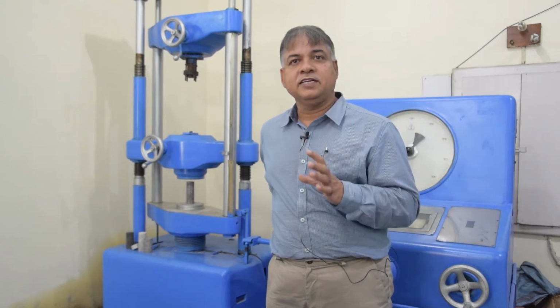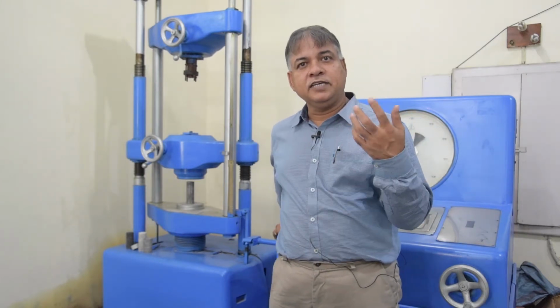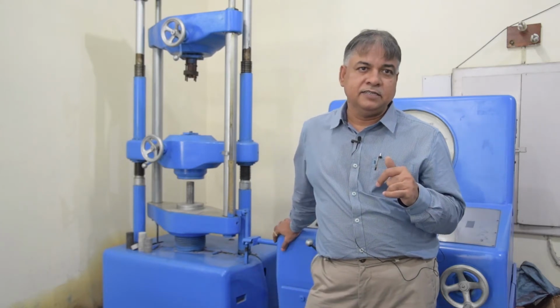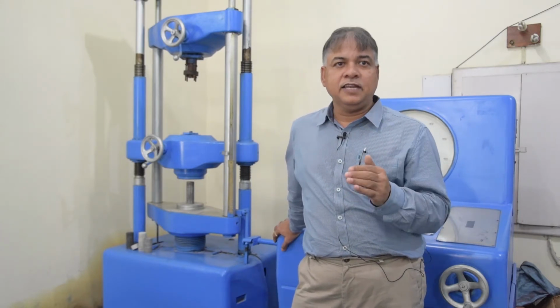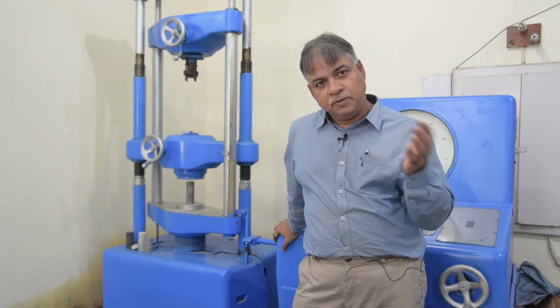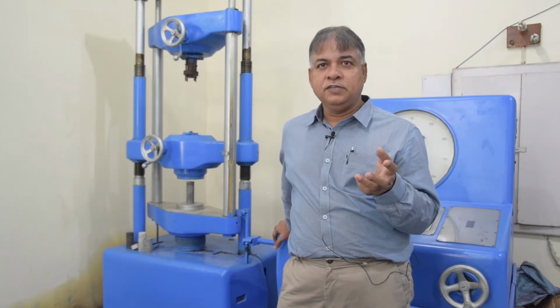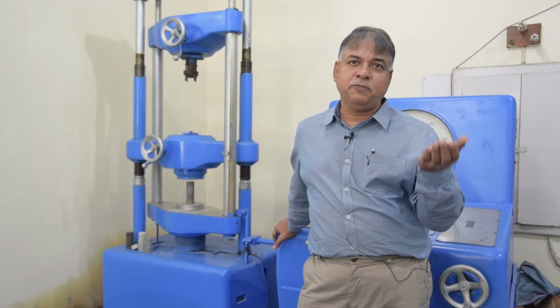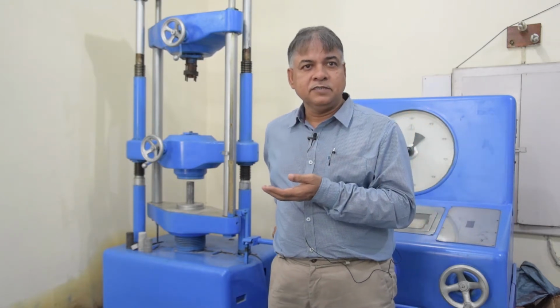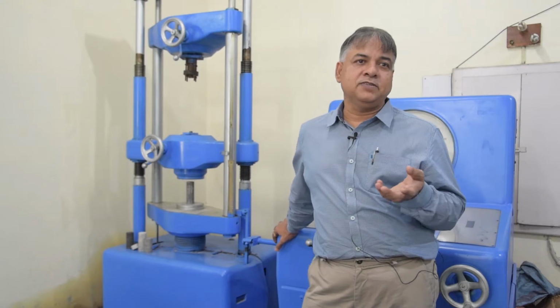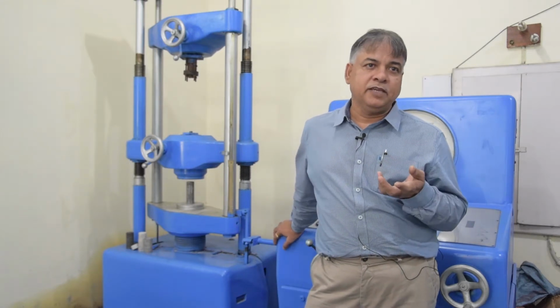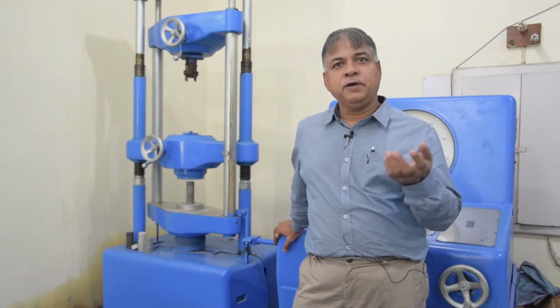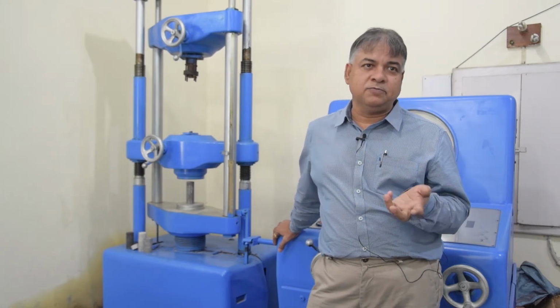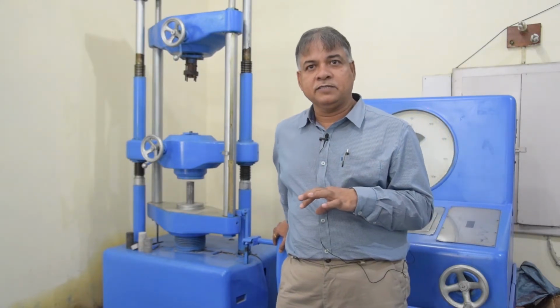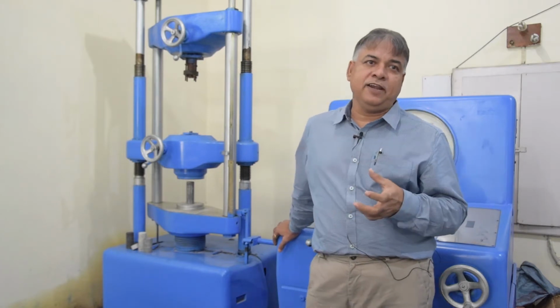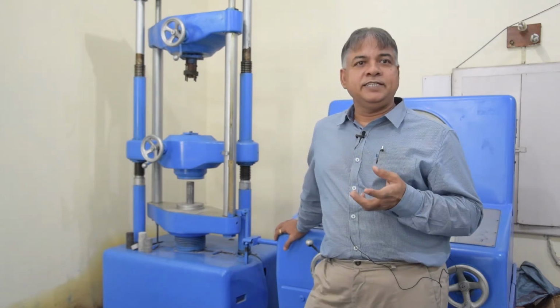12 megapascal at the maximum, because it is well established from the literature that if you compare the compressive strength in the lab with the field value, the variation ranges from 5 times to 10 times. So, if a rock is giving a compressive strength of 60 megapascal in the laboratory, in the field you might find that it is providing a strength of 6 megapascal or 12 megapascal. So, that kind of scaling effect has to be utilized during design.